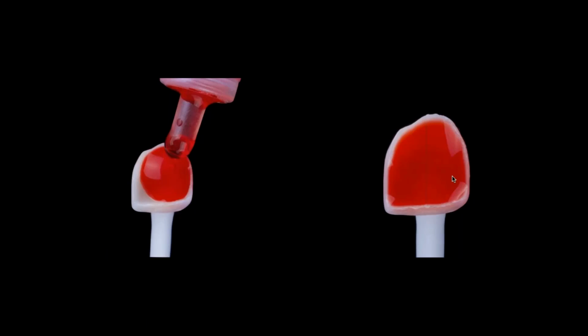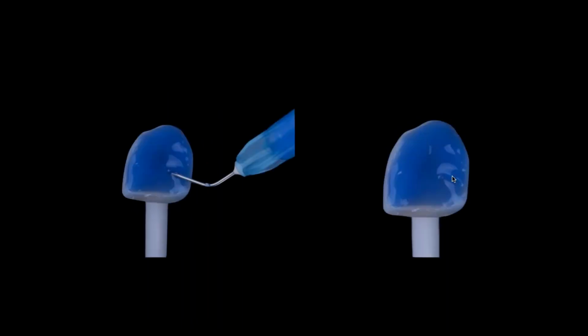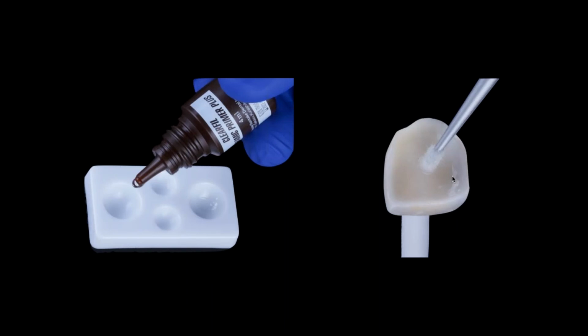So after try-in, we wash the try-in, we apply the hydrofluoric acid etching, as I said, for 20 seconds, wash, dry, you put it in the ultrasonic, or you can etch it with phosphoric acid to remove any type of remnants or residues from the etching. Okay, as you can see here, and then we can go ahead and apply the silane coupling agent. This is the Clearfil Ceramic Primer Plus, and once I apply that, I don't want to put any air, I don't want to do anything to that silane there, just let it evaporate and go and start with treating the